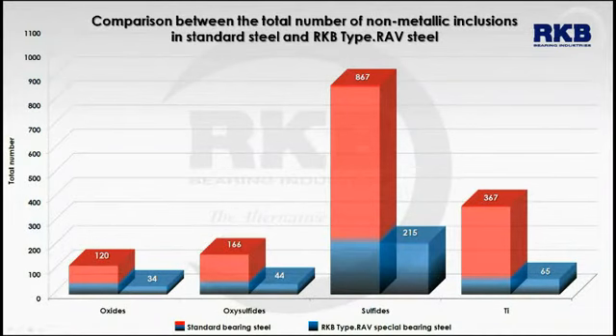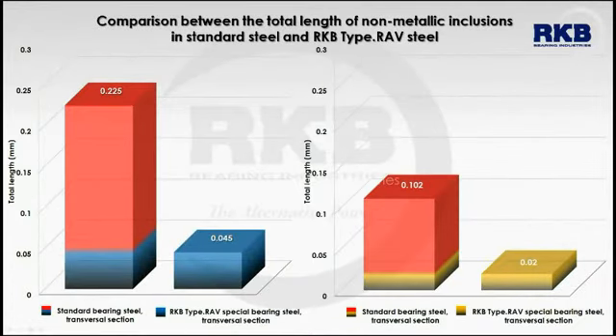Finally, as for the evaluation of non-metallic inclusions, we examined their total number and total length. This bar graph says that the total number of oxides, oxysulfides, sulfides and titanium oxides, both small size 1 to 10 micrometers and big size 10 to 40 micrometers, is much higher in standard steel than in our special bearing steel. The evaluation of the total length of non-metallic inclusions consisted in a transversal and longitudinal section inspection. As you can see, in both sections, the total length turns out to be much higher in standard steel than in RKB Type.RAV steel.